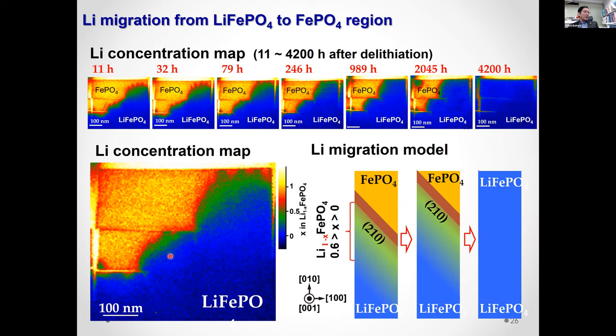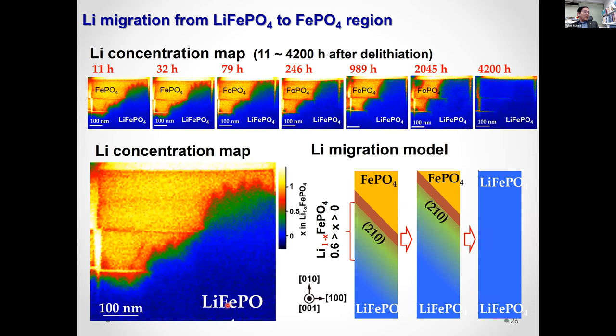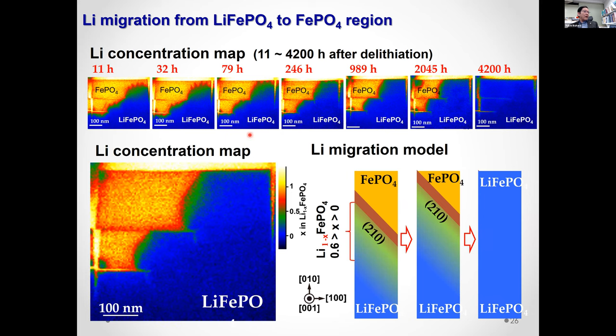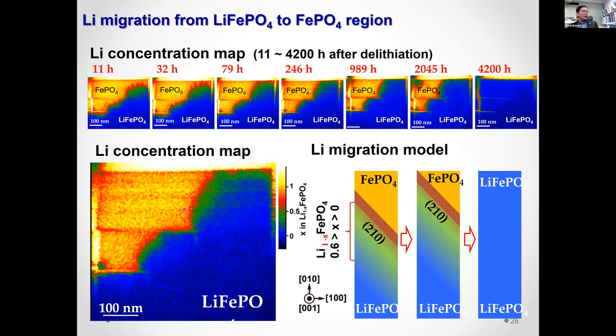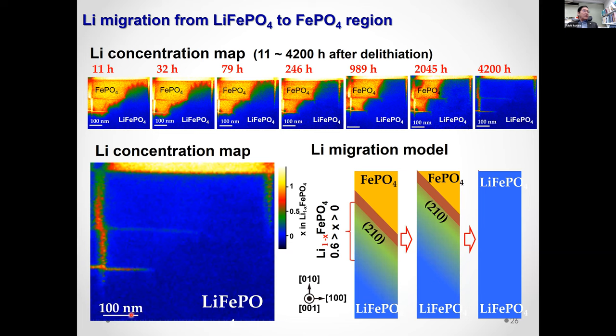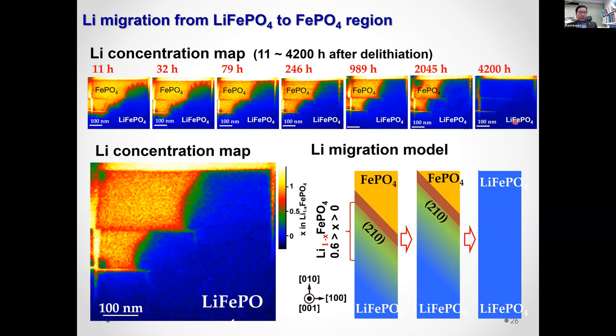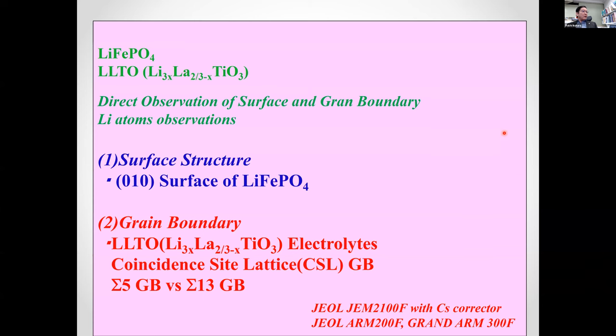Okay, this is lithium diffused from inside to the surface, first in the B direction and then in the A direction. The A direction is a little slow, but we can see this is a dynamic observation, although this is a very slow diffusion phenomenon. Okay, let me show the second topic, the grain boundaries. This is also very important.